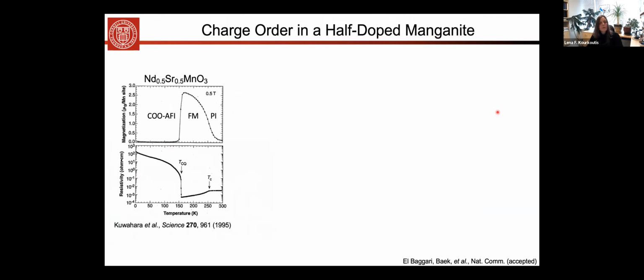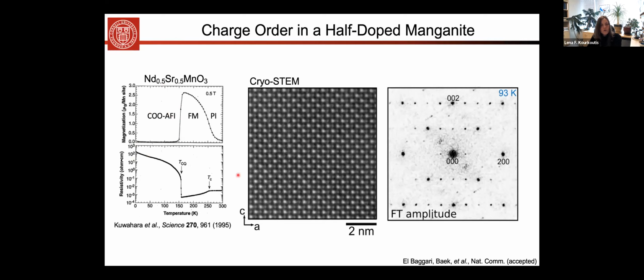So we started with a prototypical manganite. It's the half-doped system, in fact also grown at Stanford by Harold Wang in thin film form. And what you see here, at low temperature, is that you are sitting in this charge-ordered phase. Now, by straight imaging in the cryo STEM, if you take the Fourier transform, you can again see these superlattice structures that arise because of that symmetry breaking when you're in the charge-ordered phase. So we know that we are indeed sitting in that phase, and we could do dark field TEM to image our stripes or whatever structure we have in this system.